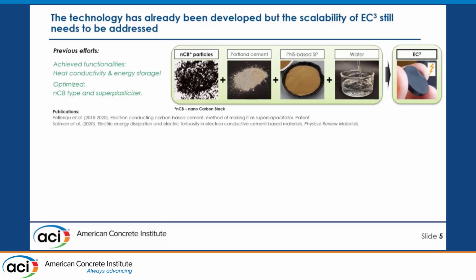How to make EC cube? We just use dry mix, adding nanocarbon particles, which are hydrophobic. So proper dispersion is the key. It clumps with addition of water, but at the same time, we don't want to disperse it to create separate islands. And the technology has already been developed, and I cannot take credit for it.